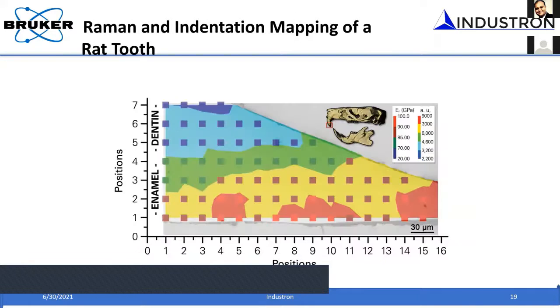If you do that, for example, you map with the Raman and measure the intensity at that particular peak, and then you indent at the same location to try to correlate: if you have a high mineral content, do you get a higher mechanical property? For example, in this case, it's just the modulus. So you can see readily that when you have a high peak intensity, when you have a high mineral content, the modulus also goes up.